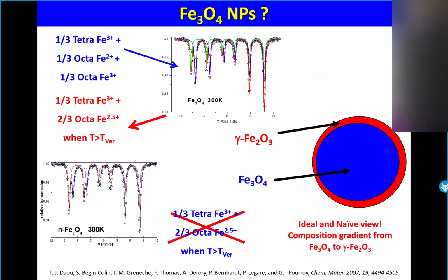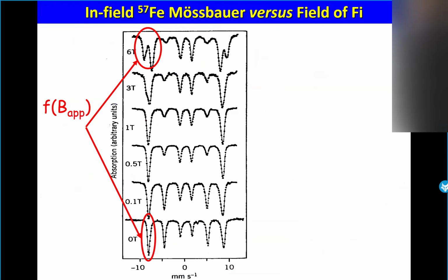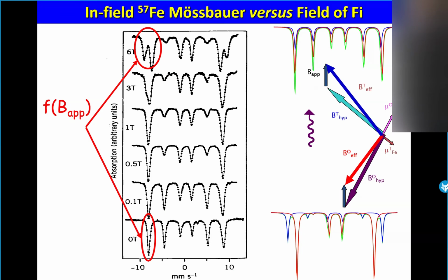And it's possible to estimate the thickness of this layer. Finally, if you have very small nanoparticles of nanomagnetite, finally, it's not magnetite, it's maghemite, because the thickness is about 3-4 nanometers. So now you apply an external magnetic field, and of course, at 0 Tesla, at low temperature, no resolved structure. But if you go up, according to what I explained this morning, we have a splitting. So it's possible to estimate tetra and octa. In this case, it corresponds to maghemite.